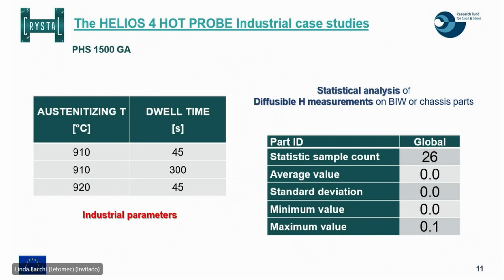Also in this case, we have reported here the statistical analysis of the measurements. We made a lot of measurements on several pieces, and the maximum value that we found was 0.1, but the average value of all the measurements that we performed was 0.0. So I think we can say there was negligible diffusible hydrogen content in almost all the pieces that we received from Voestalpine. And this is the conclusion related to the industrial measurements on components.